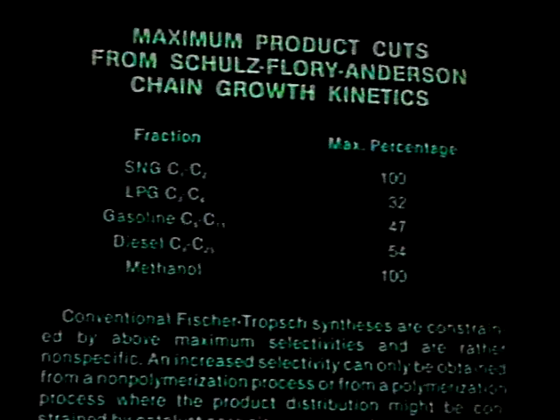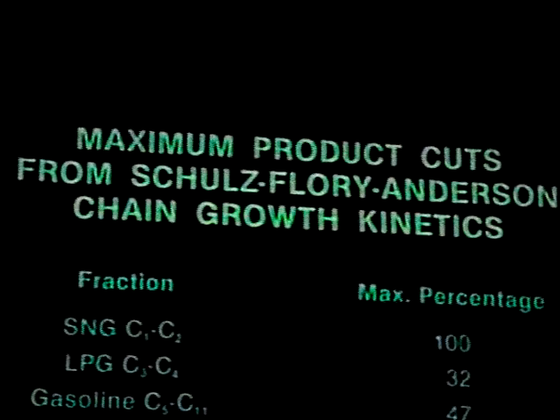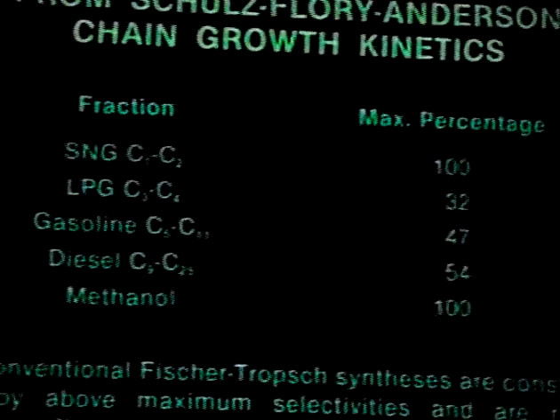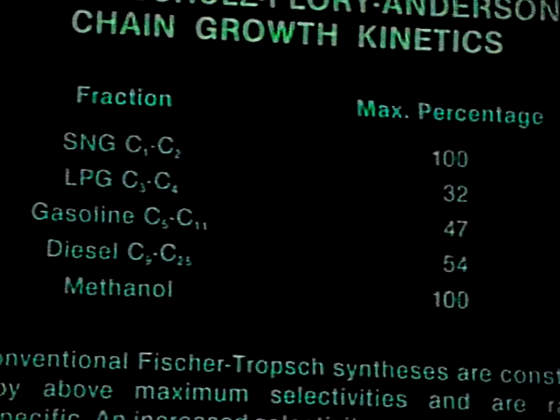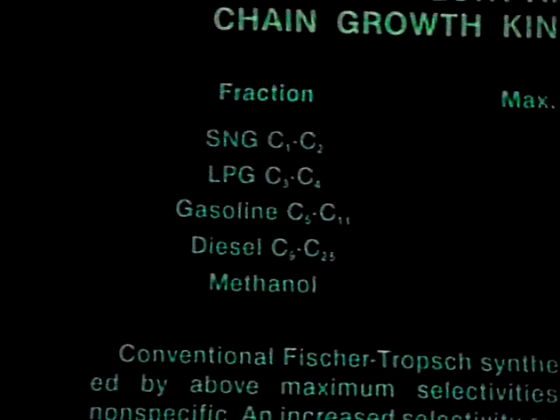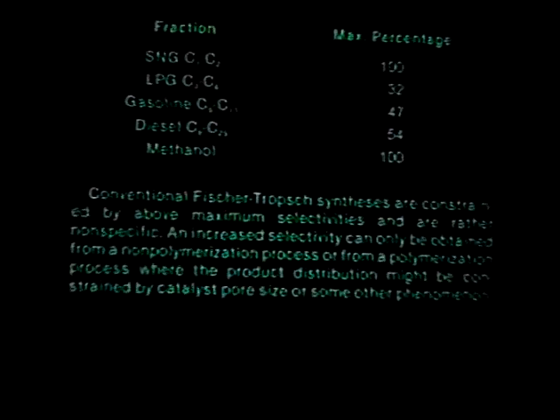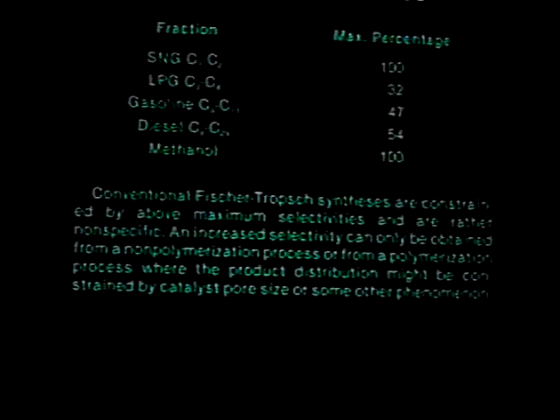The reason for doing this is to try to circumvent the Schultz-Flory kinetics, which limits the amount of gasoline that one can get in the conversion of syngas to about 47%. Therefore, conventional FT processes are constrained by these maximum selectivities, and they are non-specific. So one way to bypass it is to add a zeolite such as ZSM 5 to the catalyst, so that the intermediates are siphoned off before they can grow to large molecules. Also, the acid function of the ZSM 5 will provide aromatics, which will help in the octane rating of the gasoline.